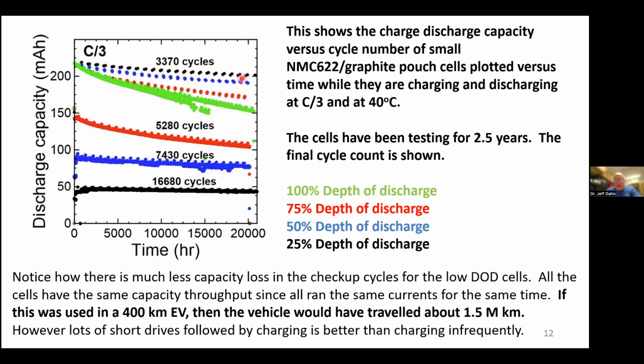When you look at these data, you can see clearly that the green, where you're doing 100% depth of discharge every time, is worse than the red, is worse than the blue, and the black, where you're doing these 25% depth of discharge cycles, the capacity decline is very minimal over this roughly 2.5 years of testing.